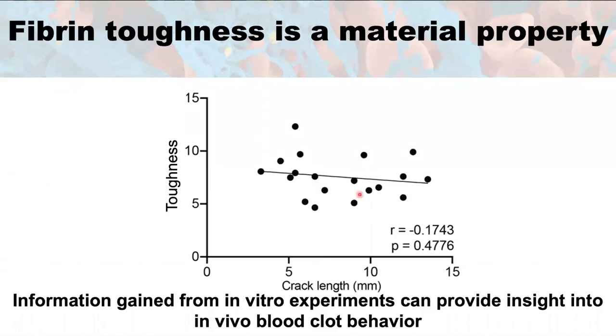So by looking at the toughness that was calculated from each individual curve as a function of the crack length, we were able to see that there was no difference or trend across the increasing crack lengths, meaning that the size of the crack did not influence the toughness of the material. And this is important because it means that if it is a material property, then it is independent of the size or of the shape of the material. And thus, information that we get from these in vitro experiments can ultimately be used to help provide insights into in vivo clot behavior, and thus help to explain the embolization mechanisms.